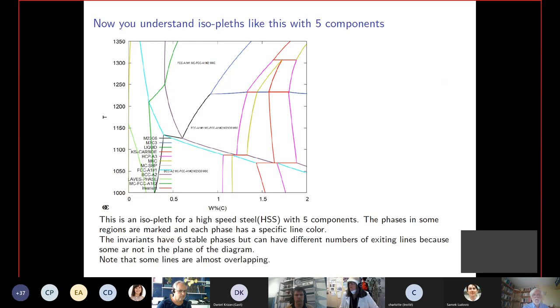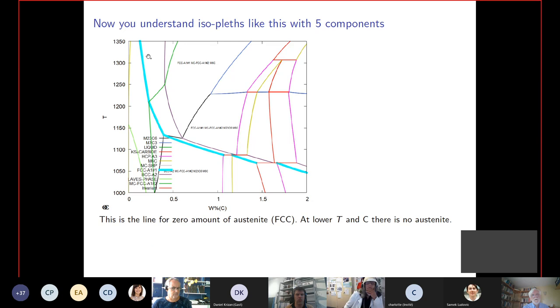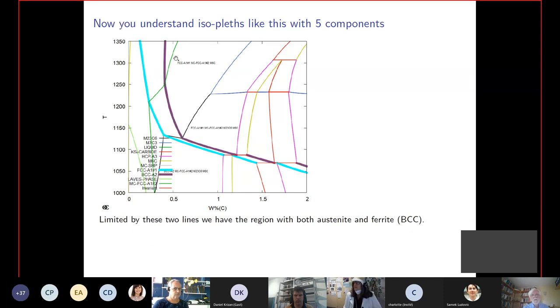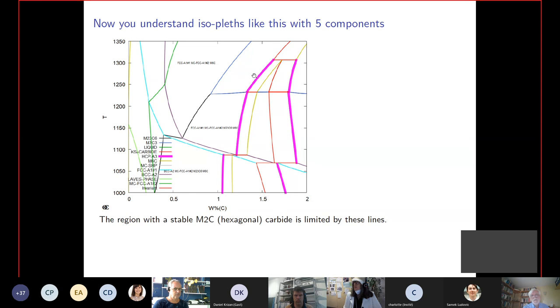So if you take a multi-component system like this with five components, you cannot really say much about the phases except which one you have stable here. But you have a line here which is where the FCC phase disappears. So FCC is stable in this region. And you have another line here which says where the BCC phase has zero amounts, so you have BCC phase below this temperature. And you can find out, for example, where the HCP carbide is stable. That will be limited by those points here.